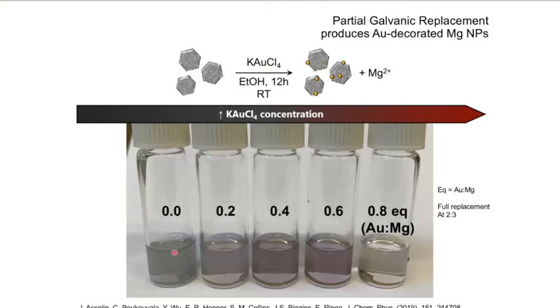Okay, so if we don't put any gold, we get our gray-green solution of magnesium. As we add more gold, the plasmon resonance of these gold particles starts to pop. If we put too much gold, well, everything crashes down and aggregates, and the sweet spot, the full replacement, actually is at a 2 to 3. So it's just here at 0.6. But if we do less than that, then we still have magnesium present as metal.